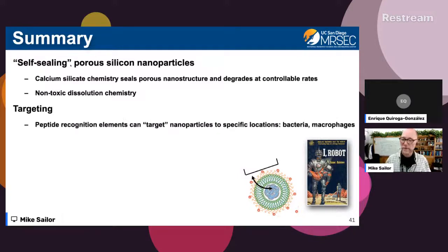And that they're really good at targeting. So we can have them target specific locations. I showed you 2 examples today of directly attacking the bacteria and targeting them, and then another peptide that was used to directly target macrophages that would then shut down an inflammatory response. With the case of the bacterial targeting, we showed that we could deliver vancomycin much more effectively, so we didn't have to use as large of a dose to get the same effect.